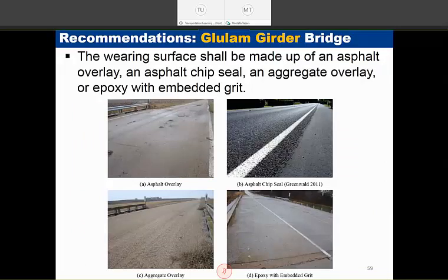Maybe one of the most important concerns that the DOT had was the overlay and how we can have a good overlay over the timber bridge. We did a literature review and also inspected 6 bridges in Minnesota and Iowa, and we have found that if you use asphalt overlay, asphalt chip seal, aggregate overlay, or epoxy with embedded grit, all of these will be viable and will work well with timber decks.